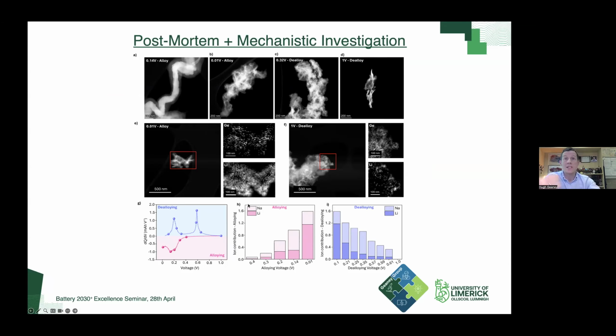As I said, it was hinted at from the electrochemical response: during the alloying, they are working together. You have lithium and sodium ion both going into the system at the same time. And by the time fully alloying is completed, you have a predominantly lithium-rich system at the end.